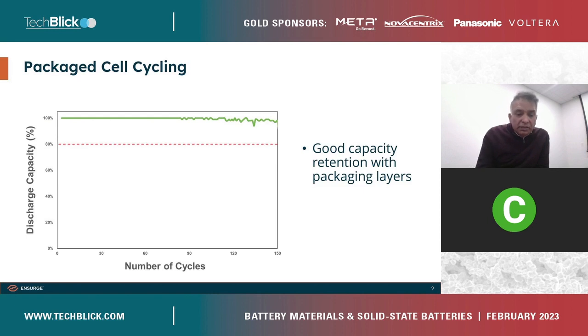And here's some data about the packaged cell, about the cycling. We get very good CEs of over 99.9% when it's packaged. As we all know, lithium essentially will react with anything, and so it's very important to have materials in the package that one will not react with the lithium itself, and two will also act as a moisture and oxygen seal so that you don't have a loss.